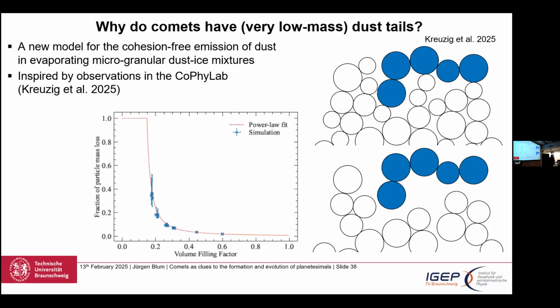The idea is the following. So here is our artificial comet, just consisting of ice. The blue color doesn't mean anything at the moment, it's just ice. So we shine light onto it, and that light penetrates very deeply. We've calculated about 100 to 1,000 of these layers deep. We are basically at the same temperature. So all is at the same temperature. So all the particles evaporate slowly into vacuum.